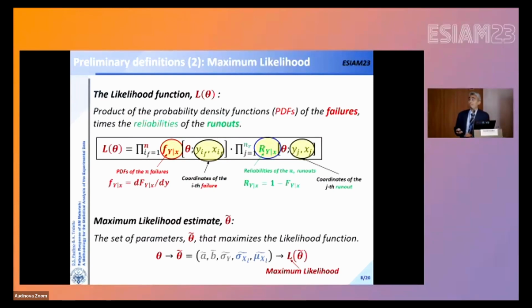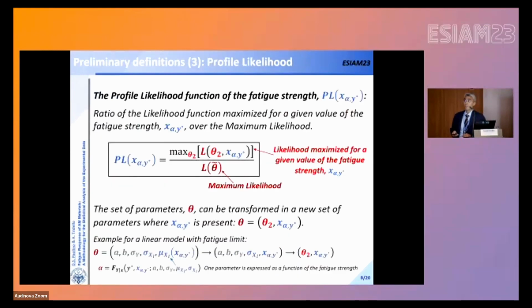This approach is quite common and easy, but does not take into account one important aspect, which is the fact that the accuracy in the estimate depends on the data set that we have. Large sample size means good accuracy. Small sample size means poor accuracy in the estimation of the parameters. So how can we take into account also the accuracy in the estimation?